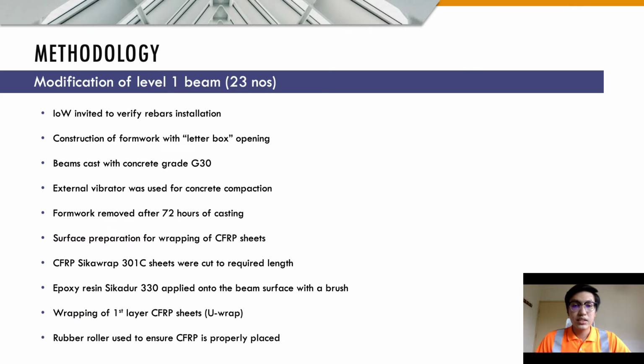All beams were cast with a concrete grade of G30. An external vibrator was used for concrete compaction. The formwork was finally removed after 72 hours of casting.